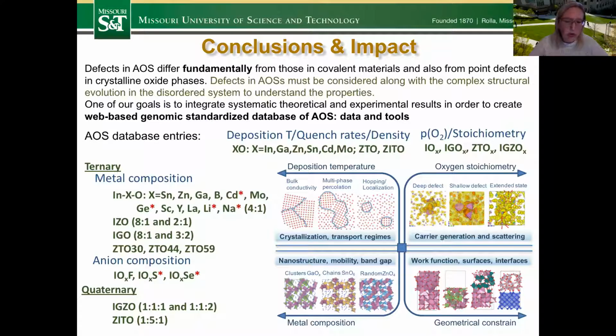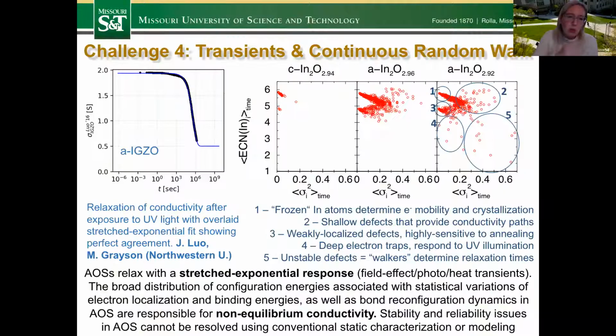But also I think the issue is that we have such dynamics in these structures. Actually, I wanted to mention, since you also let me go to this slide, that the relaxation of this conductivity is very, very long. The measurements showed, for example, for indium gallium zinc oxide, it took about 6 months to measure the photoresponse. So the dynamics in this structure is really significant, and that's why static characterization is not really appropriate for this system. Whatever we are measuring statically, if we want to get these chains, it's not enough, right? We really need to look at the transient response and the dynamics in this structure. So that's why it's very challenging to find those chains.